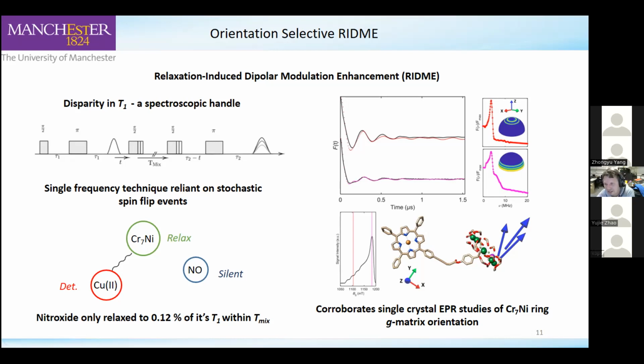What you're saying is that the linker, as let's say you go from 150, 200 Kelvin down to 10 Kelvin or 2 Kelvin, the thermal energy allows a little bit of flexibility. You have an X amount of rotamers, and as you decrease more and more, it becomes rather rigid, with an increase in rigidity. Would one be able to actually find the point of rigidity when it's introduced, or is it just a slow process? Or is there a point?